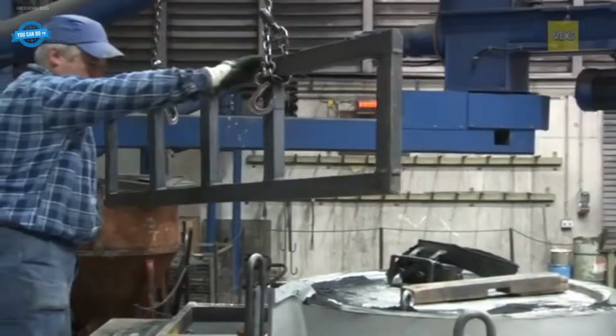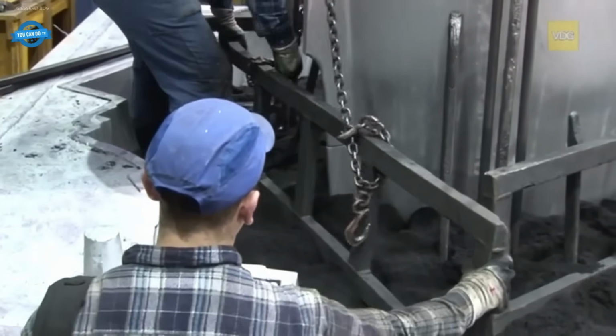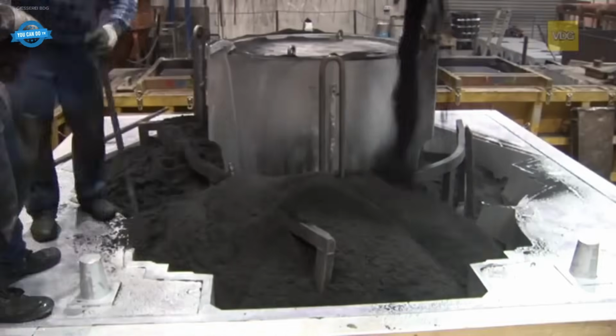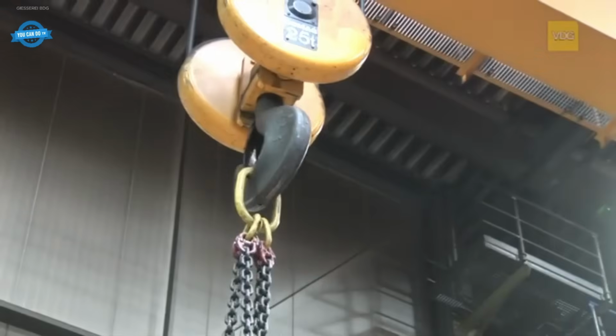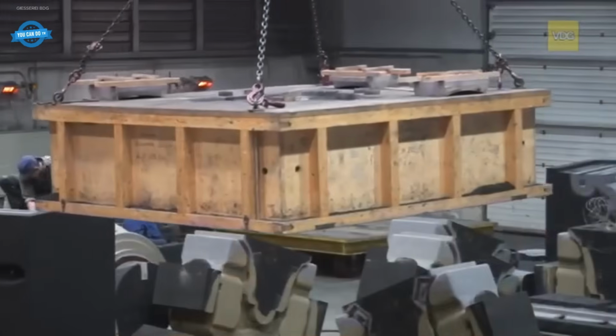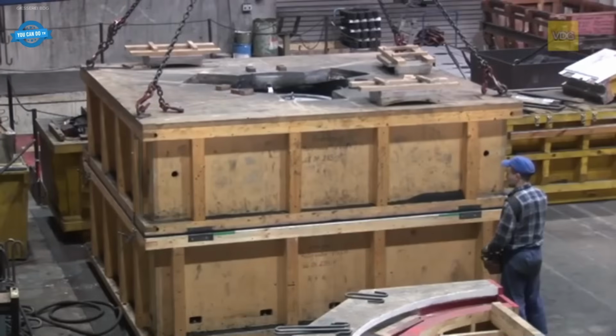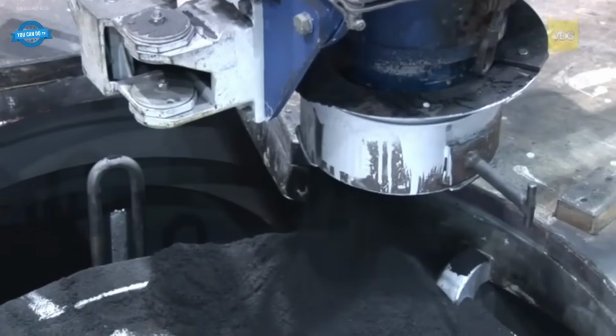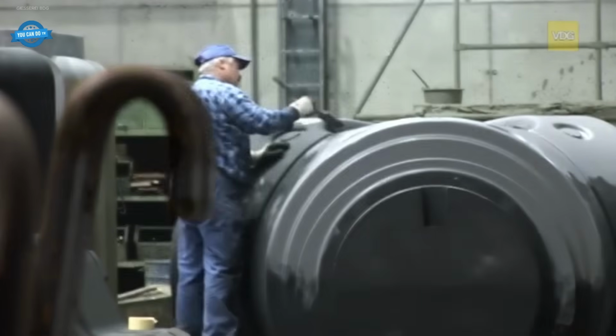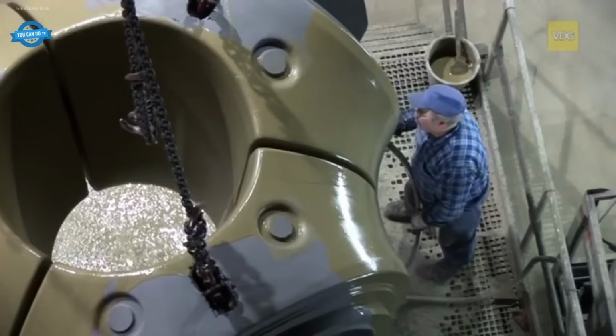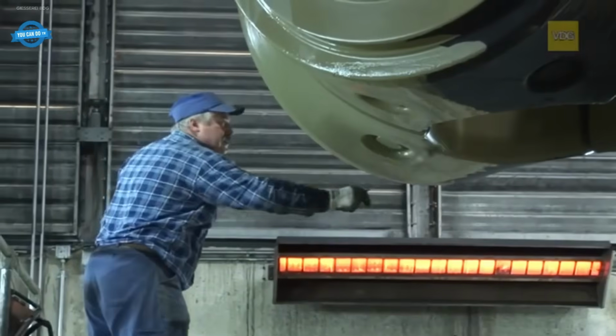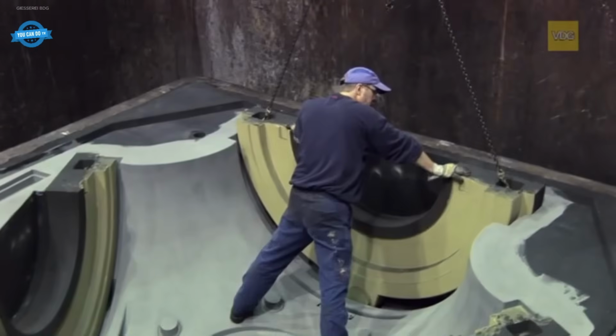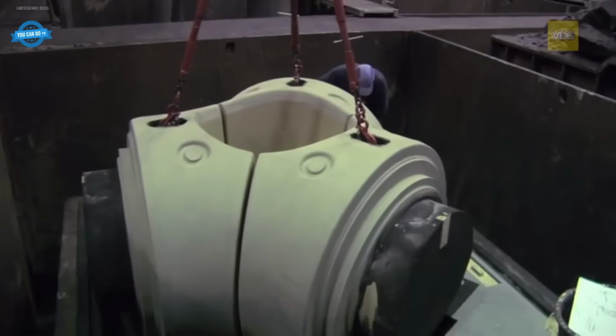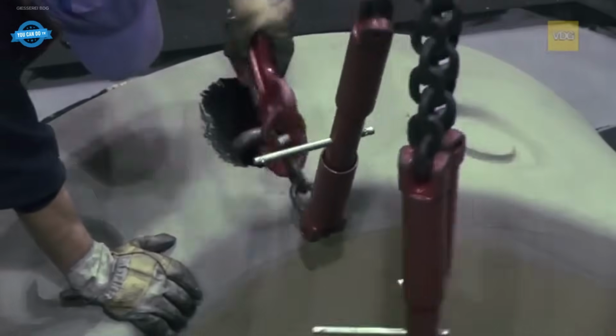After treatment, the melt is deslagged using aluminosilicate flux and filtered through ceramic strainers to capture non-metallic inclusions. The molten alloy, typically at 1370 to 1450 degrees Celsius, is then poured into the mold through a carefully designed gating system, ensuring laminar flow and even cavity filling. In high-volume cells, automatic pouring systems with thermal control ensure consistent metal temperature and flow rates.